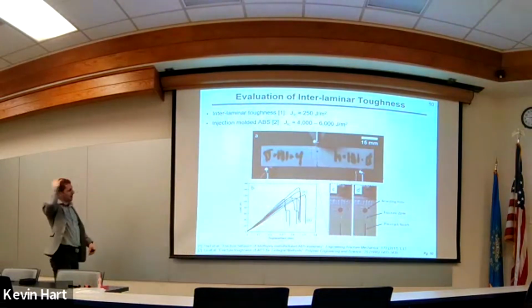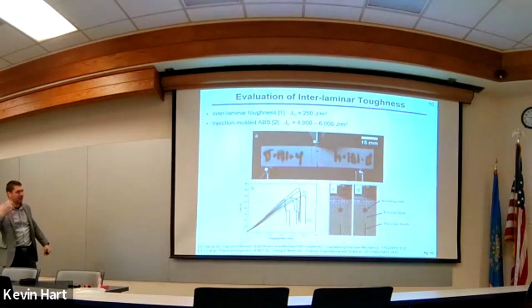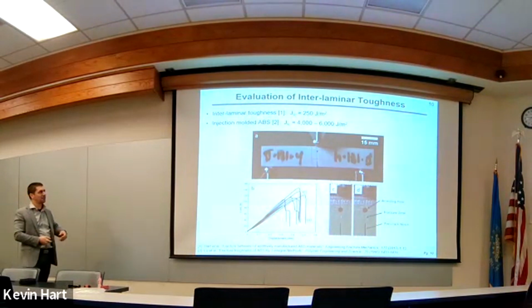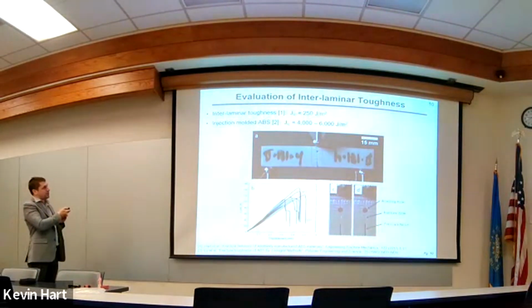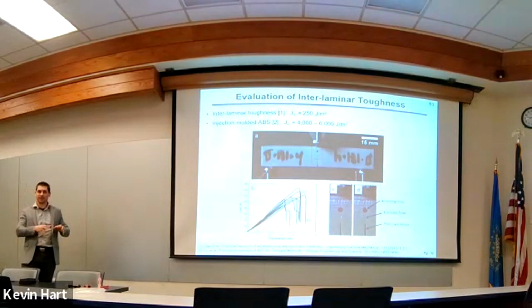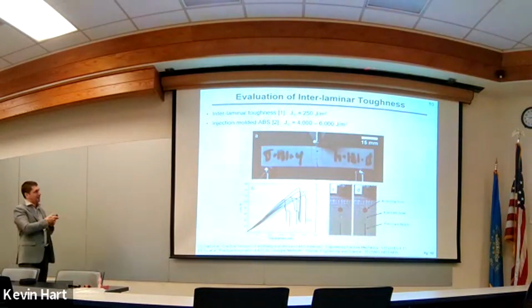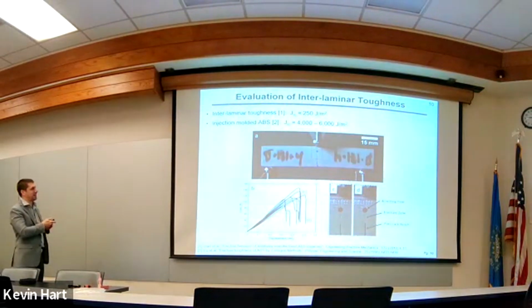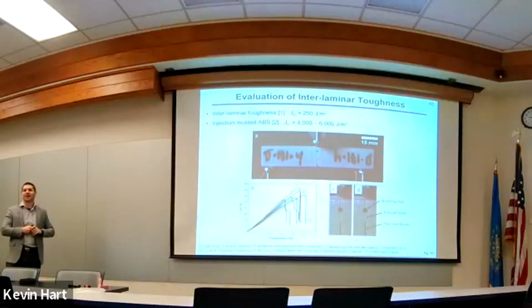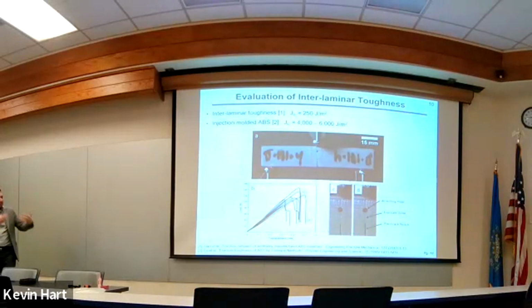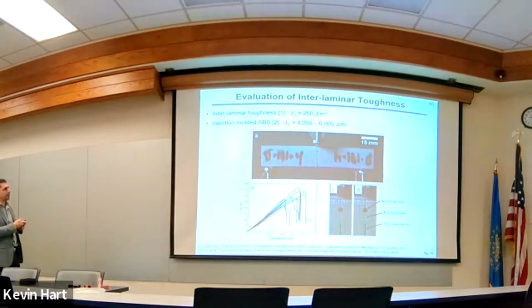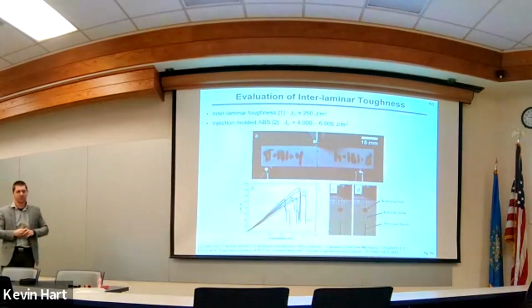All right, so we take that energy, it's the area under the curve, divided by the crack opening that we made, more or less. And we come up with a value of about 250 joules per meter squared for a 3D printed sample. So if you compare this value to this value, very easy analysis, this is big, this is small. What that tells you is that an injection molded ABS sample has a toughness of about 4,000 to 6,000 joules per meter squared, but the interlayer of a 3D printed sample, 250 joules per meter squared, is very weak. That interfacial strength is very weak.